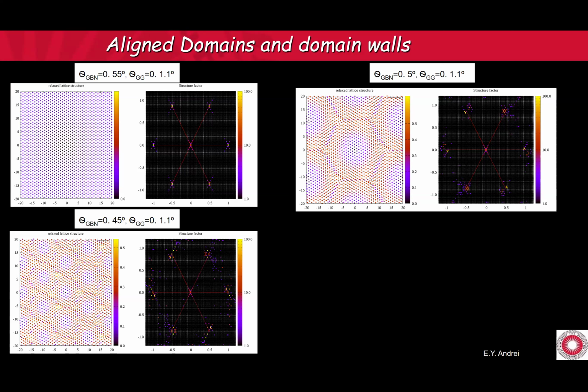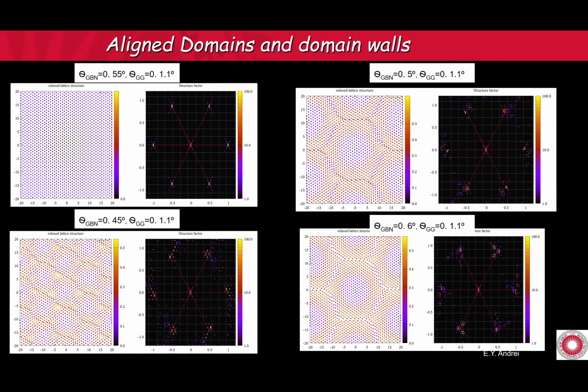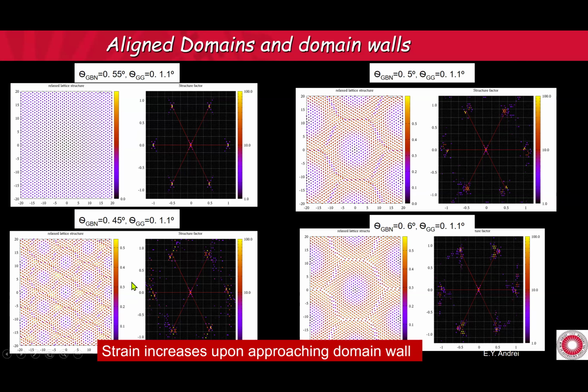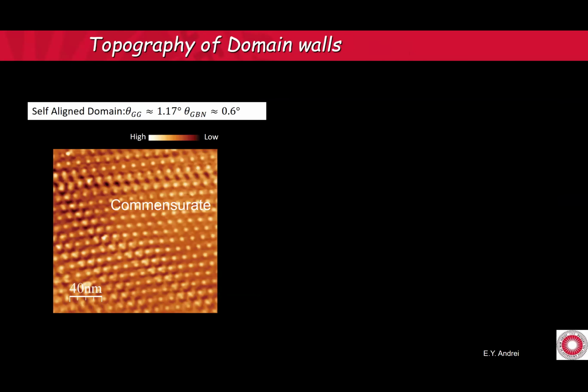Now here you're 10, here you're 20% away. So the domains keep shrinking, and as you go further and further, they become smaller and smaller. So that's the point. You can get alignment, but you cannot get global alignment. You're going to break up your sample into regions that are aligned, separated by regions that are aligned in a different way. And they're separated by these boundaries. So let's look at such a boundary. And strain increases upon approaching a domain wall.